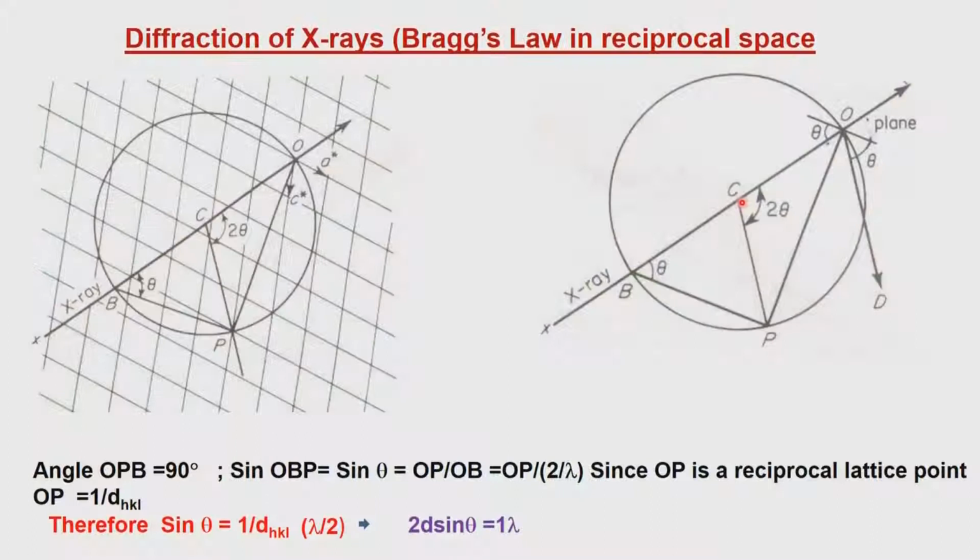So if we go back to this position, we discussed the issue that this is a stationary reciprocal lattice, and in the stationary reciprocal lattice we have occasional intersections of the Ewald sphere with the reciprocal lattice point, and whenever that happens we get scattering. But when we rotate the crystal about the center of the diffractometer and the crystal rotates, the reciprocal lattice also rotates with it. So as the reciprocal lattice rotates, different points on the reciprocal lattice will have the intersection with the Ewald sphere.